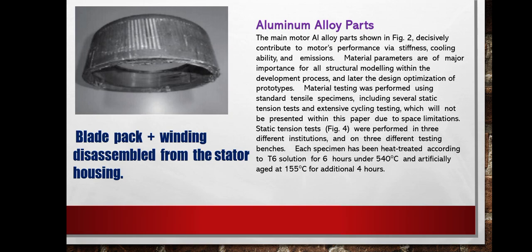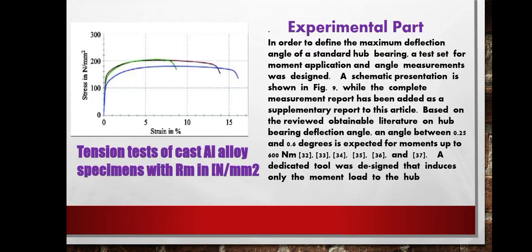Static tension tests were performed in different institutions and on three different testing benches. Each specimen was heat treated according to T6: solution treatment for 6 hours at 540 degrees centigrade and artificially aged at 155 degrees for an additional 4 hours. Now, this is the graph which indicates the tension test of cast aluminum alloy specimens with Rm in Newton per mm squared. It indicates the stress and strain relationship, and we can see there is a slight increase in the graph and a bend at failure. While the material is in the failing state, the bend occurs.